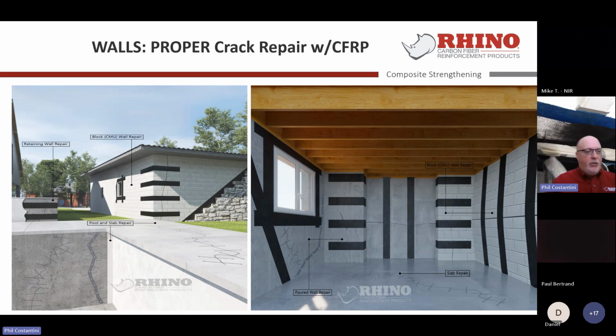Well, let's look at two things here. One thing that carbon fiber won't work on is a crack that's not repaired. What I mean by that, and we're going to jump into that very soon, is that with every application of carbon fiber, when there's a crack in the wall, that crack has to be dealt with first. In the case of masonry, if it's a bowed wall, then of course we'd have to chip out the masonry up to a certain profile of bowing in that wall. But if it's a poured wall, you're going to see in my prescriptive methods moving forward, I'm going to demand that it get injected with epoxy.